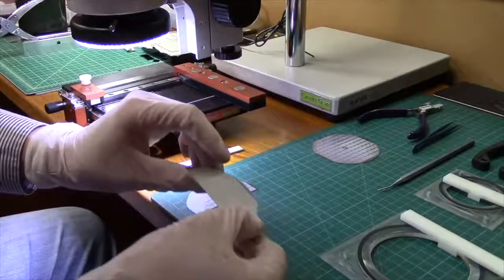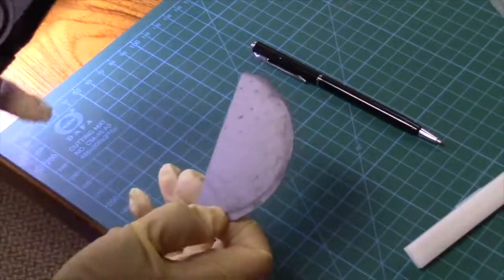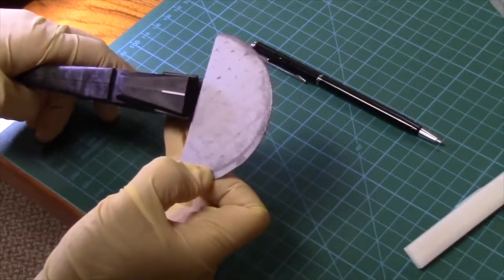We have seen the best cleaves come from scribes made with only one pass and that are not too deep. This is dependent on the thickness of the wafer and depends on your use case.